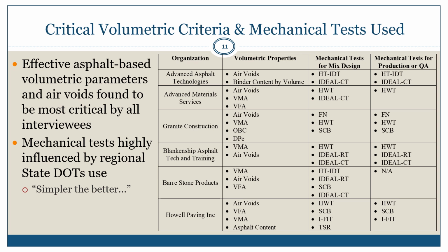The other thing that we asked our interviewees is what are some critical volumetric criteria that you believe we really shouldn't take out of our specifications right now, because they do provide a large benefit in how to redesign or change during production to make sure that the materials are meeting performance. You can see here air voids being a very critical one, how the material is compacting. Binder content by volume or effective binder, with your VMA and VFA, all seem to have been very consistent markers from a volumetric perspective that our interviewees identified. Even though they are using mechanical tests, these are some volumetric properties that they don't want to take away right now out of the specifications because they do believe that they provide extremely good guidance on mixture performance.